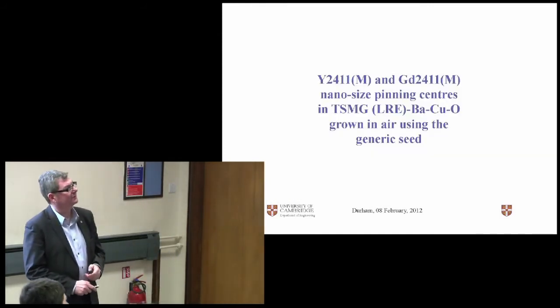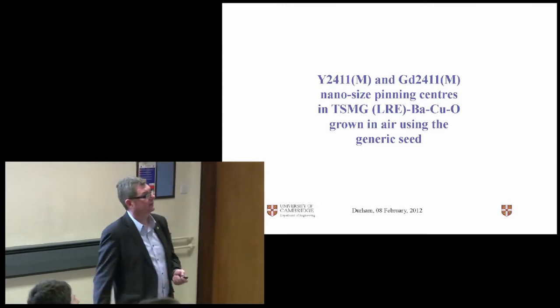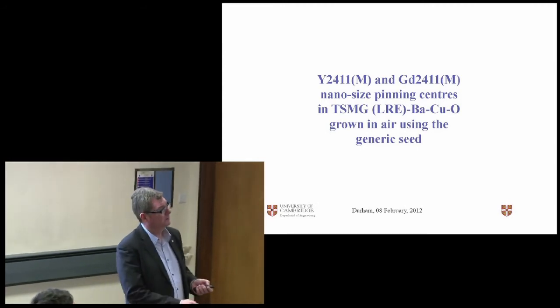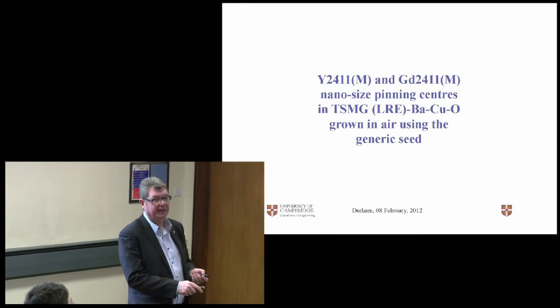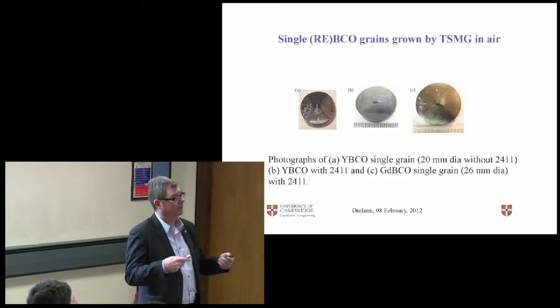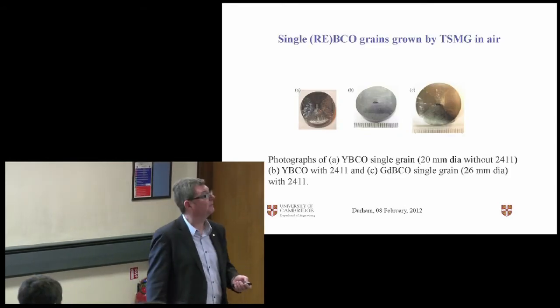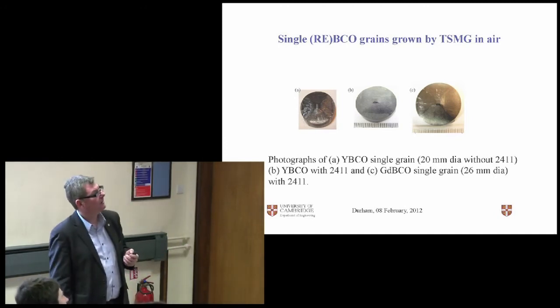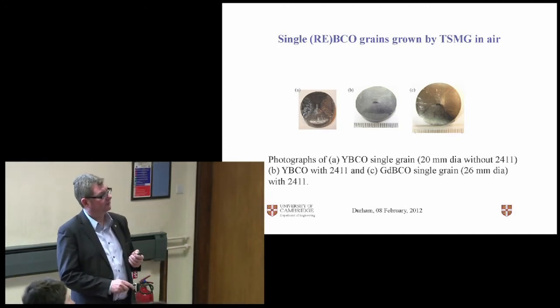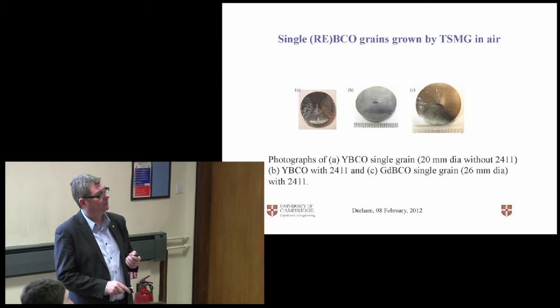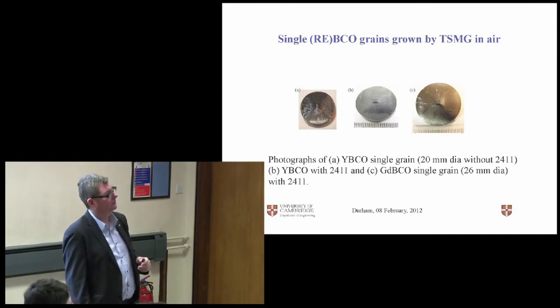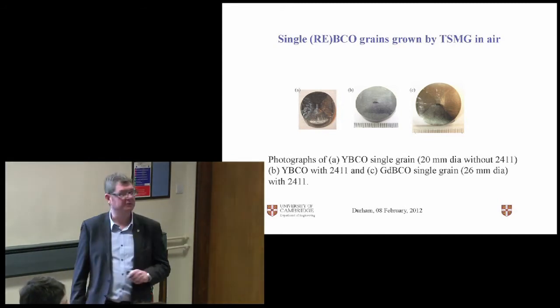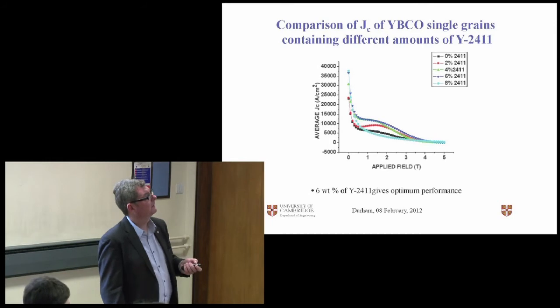Okay, so what about the properties of those samples? We're going to look at yttrium-2411 and gadolinium-2411, and we're going to use a material that's grown in air using the generic seed, so no specialist processing atmosphere. And here are just different materials. We've got yttrium barium copper oxide, single grains with and without 2411. We've got a gadolinium single grain with 2411. So the point there is we can virtually make anything out of any composition.